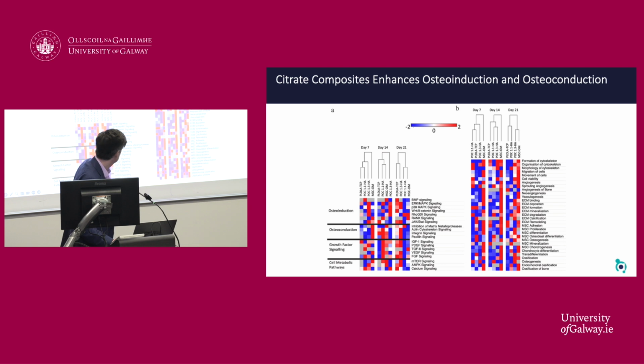significant upregulations in osteoinduction, but also really encouraging in the deposition of mineralization and the calcification of the extracellular matrix. Again, it's exactly what we wanted to see. At the transcriptome level, these MSCs were starting to induce processes that were indicative of the deposition of mineralized matrix, or bone tissue, essentially. So we were encouraged by that, and we then went to perform an in vivo study.